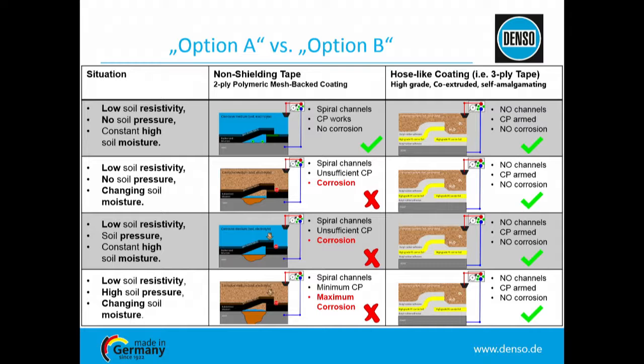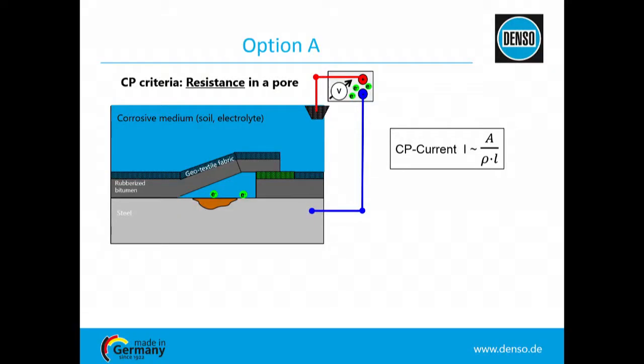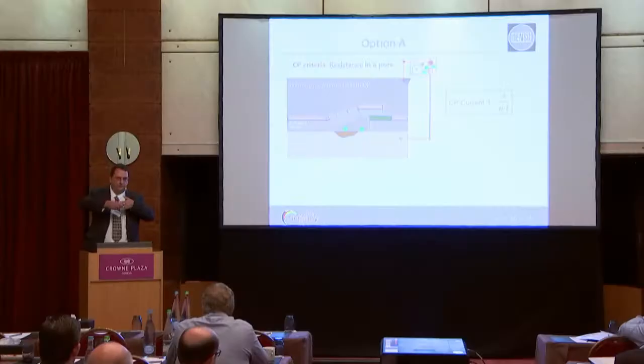The thing is, I have to go back somewhere else. Okay, Thomas, I know, but you have water and oxygen. This is not my question. I want to explain why it disbonds. Because you bring water to the steel surface, and water disbonds with time. I'm not talking about days, I'm talking about years and decades. And this path of water is not available for the three-ply tapes, because, as I showed you, you have this inter-amalgamation process. That's the answer to the question.